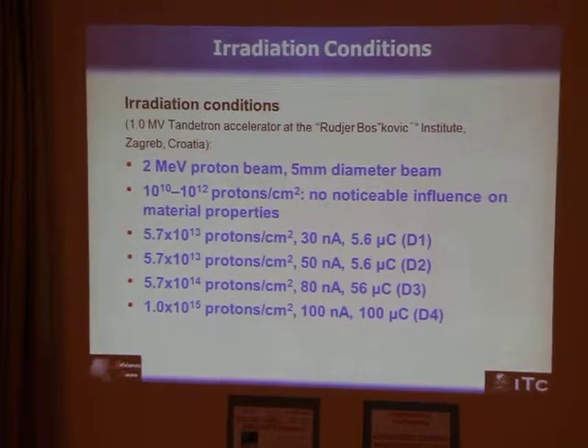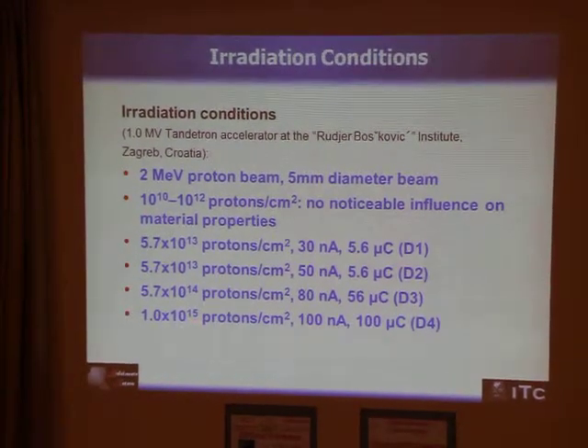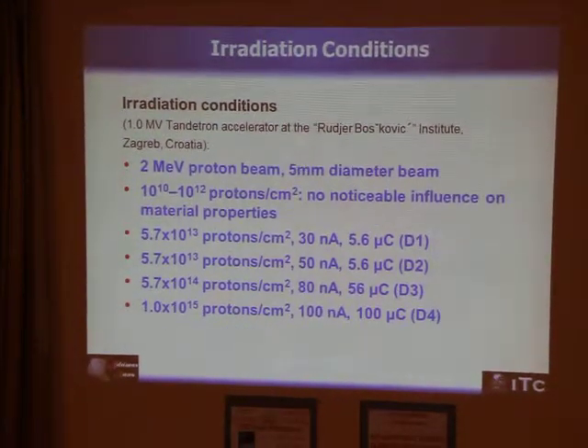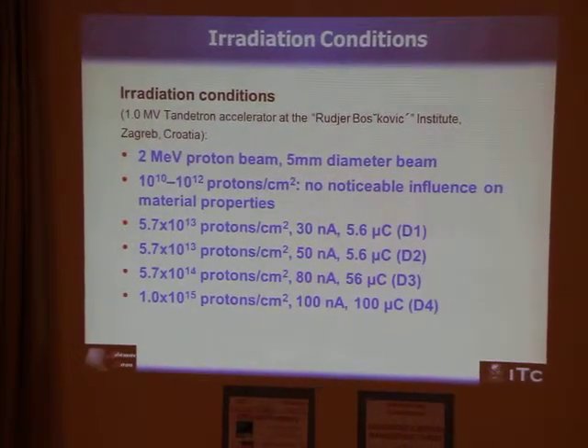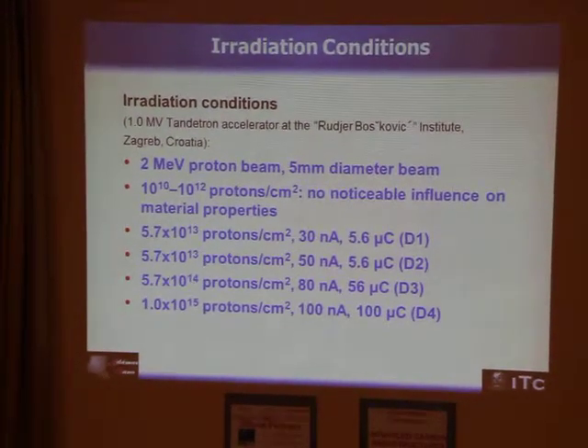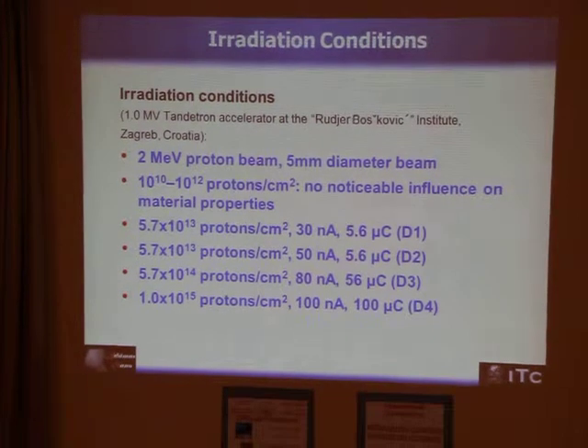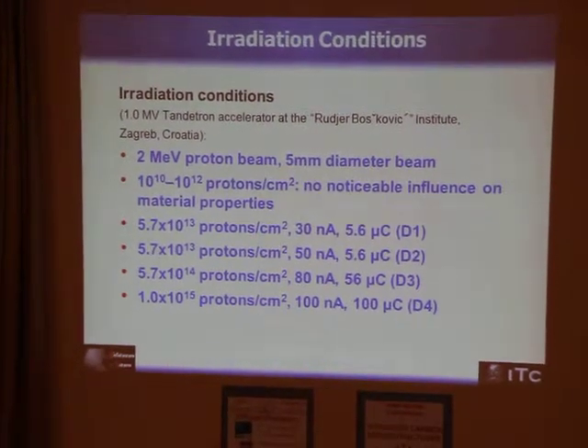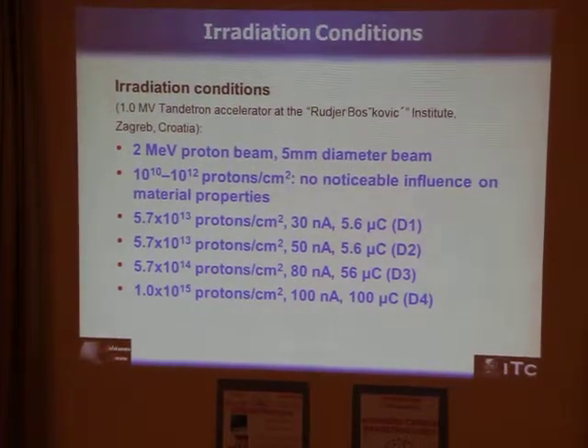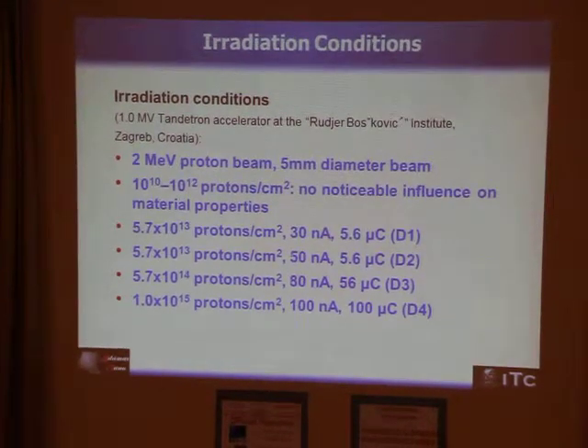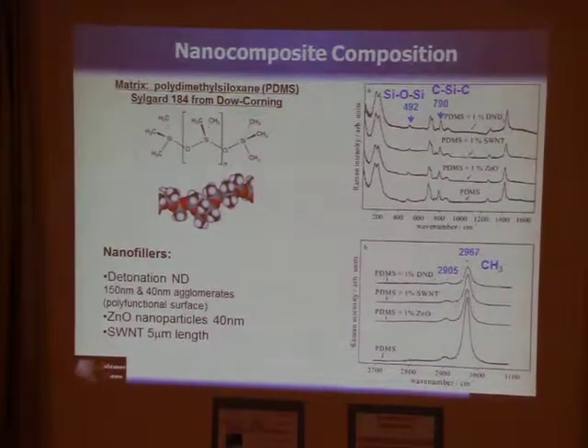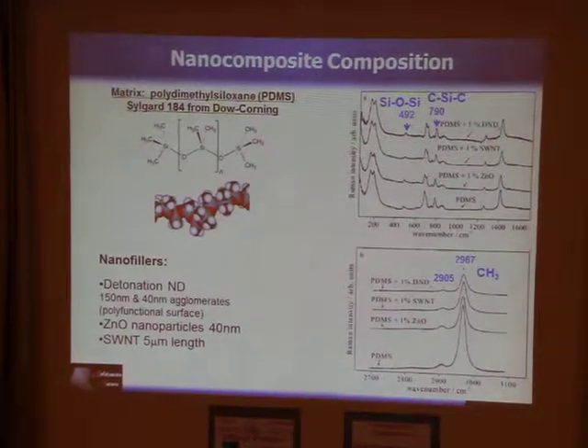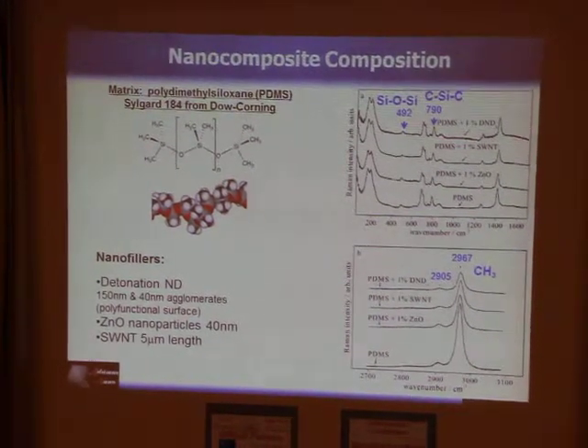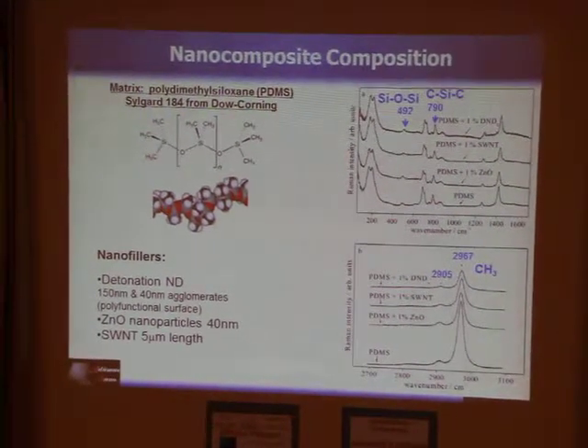And I also would like to mention that this higher dose corresponds to several weeks of operating of a spacecraft at a low Earth orbit. So what might happen with a polymer within weeks of operation. As a polymer matrix, we used polydimethylsiloxane, PDMS, matrix.